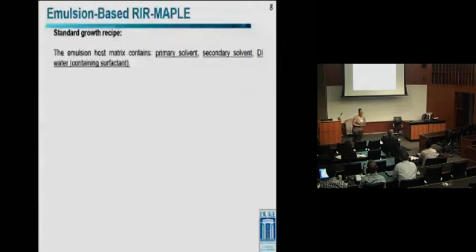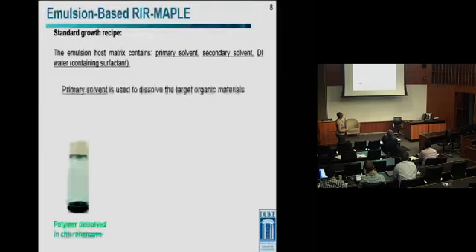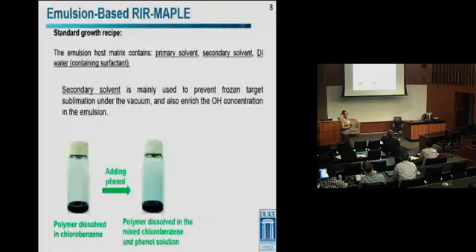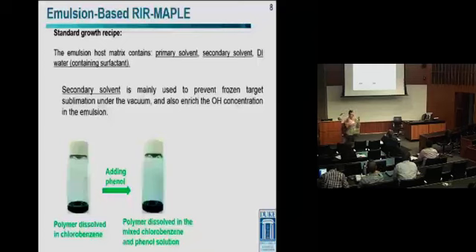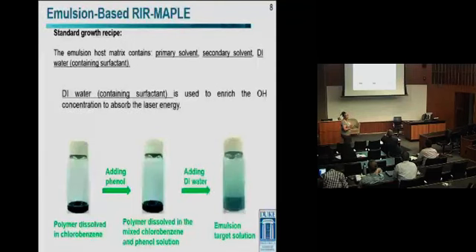So the emulsion part, I've talked about that a little bit, but just to give you a better idea of what I mean, we have many components in this emulsion that makes up the target. First we have whatever our guest material is, a polymer, dissolved in some solvent that it likes the best. In this case, let's say chlorobenzene. This is called the primary solvent. It just dissolves our organic material. And then we have a secondary solvent. In most cases, we've been using phenol. This secondary solvent, we think, is doing two primary things. One, we're enriching the amount of OH bonds present for this laser absorption. And second, it's a less volatile solvent so that we don't have direct evaporation of the target in this vacuum system. And then third, it is an emulsion. So we add the DI water, and we do have to include a surfactant in that process to make the emulsions and to get our emulsion target.